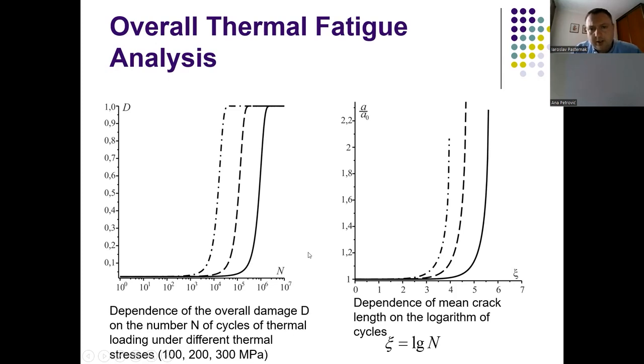When we analyzed those two models, we have obtained mainly the same dependencies of the mean crack length on the logarithm of cycles, depicted in the picture on the right. We can see that the cracks are initiating and the growth of cracks begins when the number of cycles is bigger than a thousand or ten thousand or one hundred thousand for different loading.